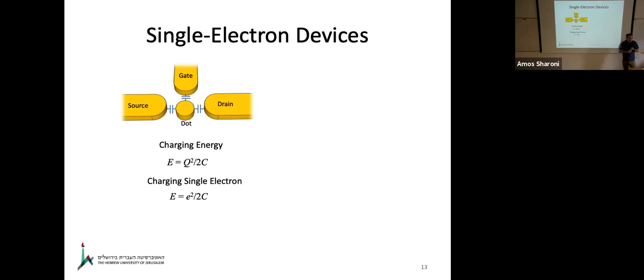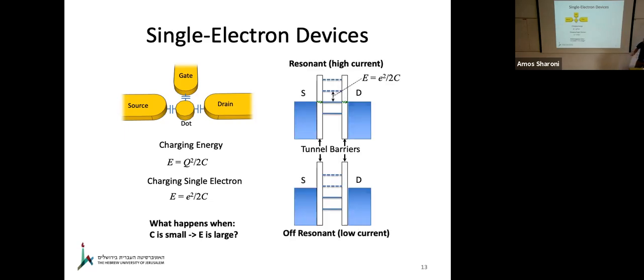That means it's going to be greater than temperature, most significantly greater than the confinement energies, the solution of the particle in the box, the orbital energies. So you are dominated by this capacitive energy. And what this means now is that you can make the following drawing, and this graphical drawing is what I'm going to be using for the rest of the talk here.